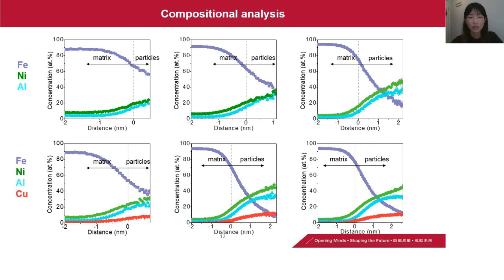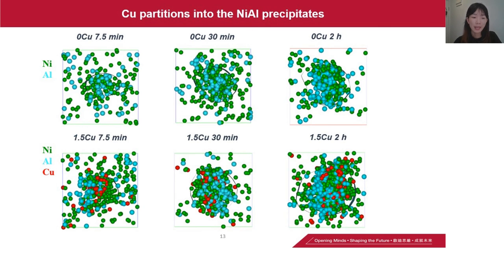Well, to deeply understand the underlying mechanisms of the effects of copper on the nickel-aluminum precipitates, we calculated the proximity histograms. It is clear to see that in the copper-added steel, the copper partitions to the nickel-aluminum particles. Well, from the atom maps of the center of some representative nickel-aluminum particles in all conditions, we can clearly see that the copper atoms, the red atoms, are partitioned into the nickel-aluminum precipitates.